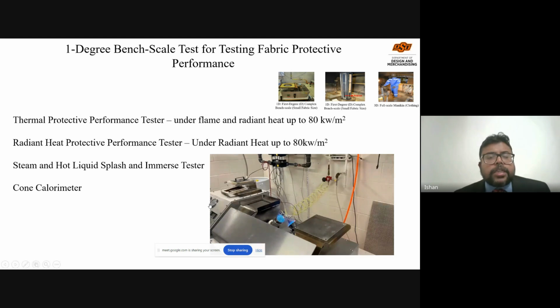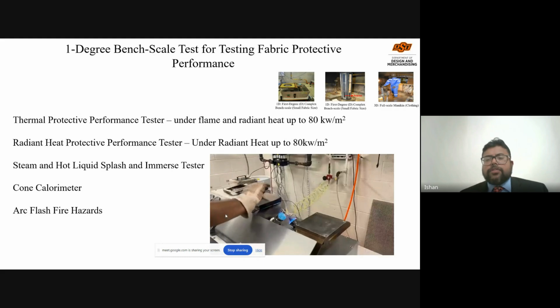Even though all of these test standards are there, I still like to mention the cone calorimeter. Cone calorimeter is not related to the thermal protective performance of our textile material, but it could give quite a lot of properties: how much heat has been released by the material, how much smoke has been generated, what will be the time of ignition. All those parameters we could get from the cone calorimeter. There are also arc flash fire hazards, especially for electrical workers. Nowadays, it's a big challenge. Arc flash hazard testing is also done at 80 kilowatt per meter square. So when we check this one, I'm just trying to show you a video on how it occurs.